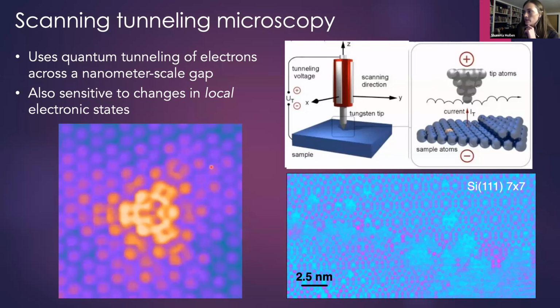Okay, so the other thing I wanted to tell you about STM was that in addition to being able to image atoms, because we're using electrons to probe the surface, we can also image changes in the electronic structure in the surface. And an example is this feature here. It's this beautiful triangular shape. The atoms are in rings, like around this circle right here would be a ring of silicon atoms. So this structure is not an atom. This is not due to atoms. This structure is because there are like electron orbitals hanging out here, and we're imaging the orbitals around the atoms.